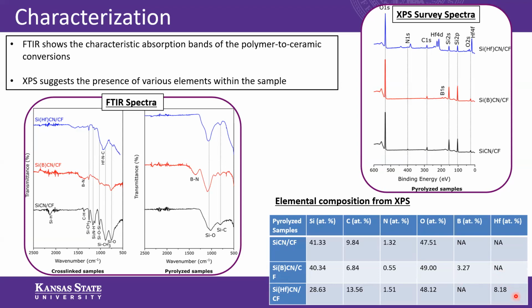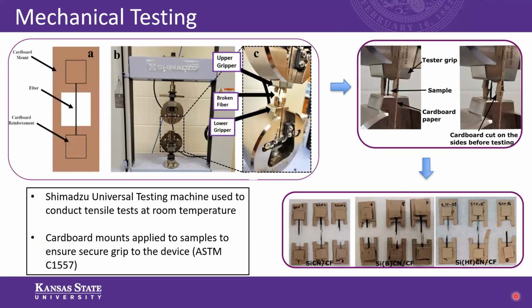And mechanical testing is as follows. For mechanical testing, a Shimadzu universal testing machine was used to conduct tensile tests, and this was done at room temperature. So this is the device that was used. Before loading, samples were mounted onto a cardboard mount, following ASTM C1557 guidelines. And this was mainly done to produce a better grip onto the tensile grippers.